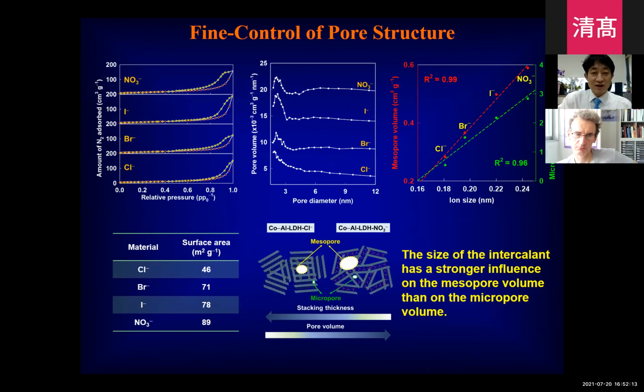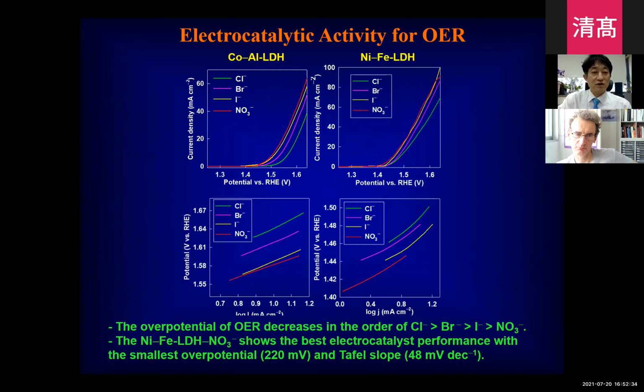Due to the thinning and the formation of defects, the reassembling with the bulky anionic species leads to the increase of surface area of the LDH nanosheet. So it's valuable to enhance the catalyst and electrode performance of the LDH nanosheet. We applied those restacked LDH as an OER catalyst, as you can see here. Restacking with nitrate shows much better performance than the LDH material restacked with chloride ion.